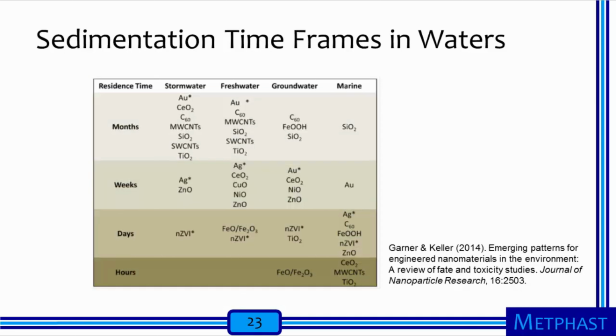The same authors classified timeframes for sedimentation for various engineered nanomaterials in different types of aquatic systems. The trends were similar, though not identical, to the aggregation timeframes. In general, sedimentation was fastest in seawater compared to stormwater, freshwater, and groundwater. Zero-valent iron and iron 2,3 oxide nanoparticles generally showed the fastest sedimentation rates across all of the aquatic systems. However, cerium oxide nanoparticles, multi-walled carbon nanotubes, and nanotitanium dioxide all demonstrated sedimentation timeframes of just hours in seawater.